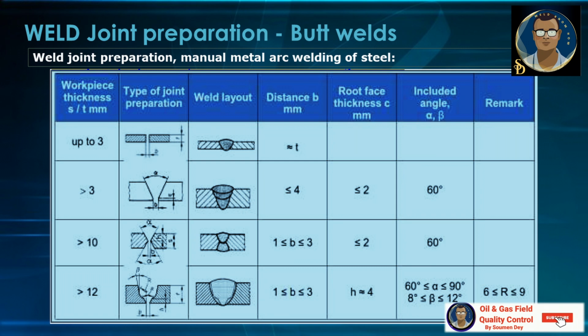If it is greater than 3 mm, then it will be a single V. There will be an included angle which is equal to 60 degree. There will be a root face less than or equal to 2 mm. The root gap will be less than or equal to 4 mm. You can see there are three layers of welding depending on the thickness of the test piece.